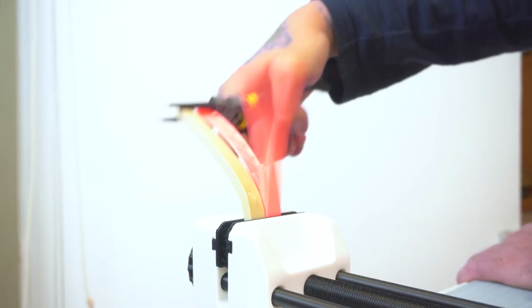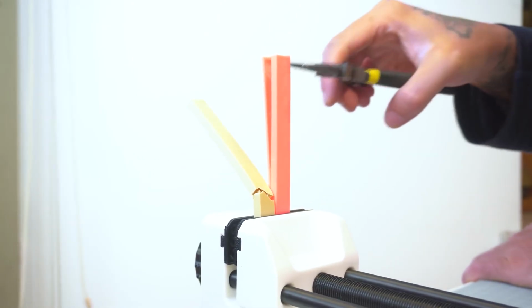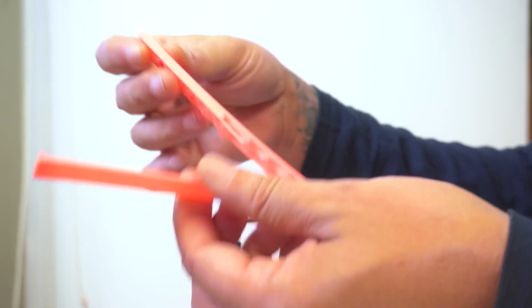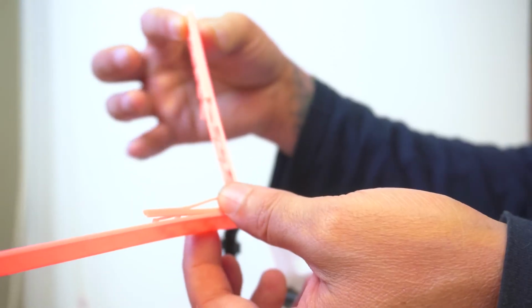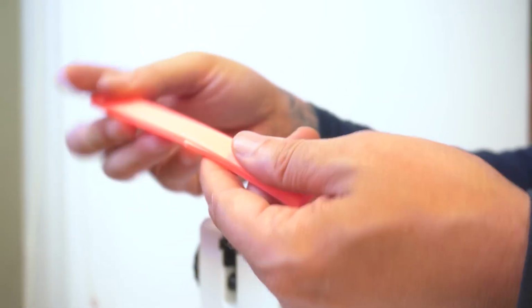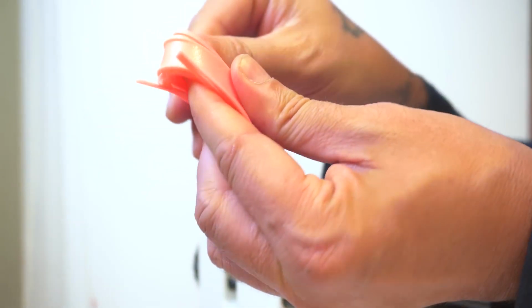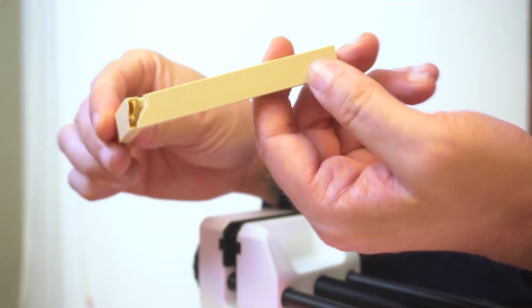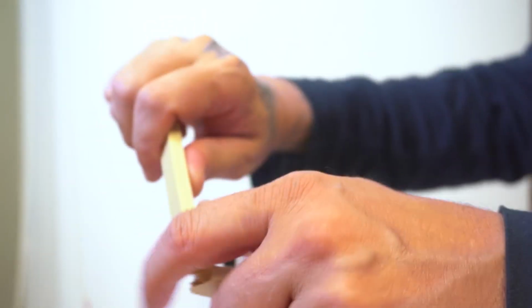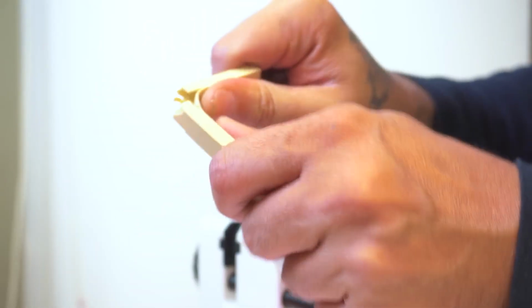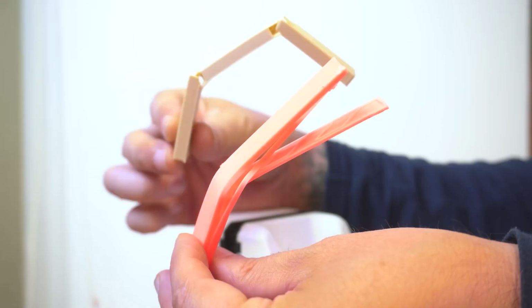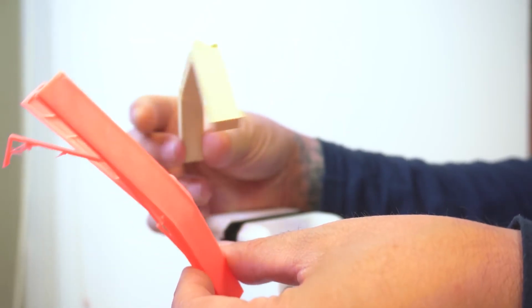we can see the normal PLA, it's completely destroyed. All the layers came apart and there is nothing to use here. Well, and the noise says it all. But the HT-PLA, it's still pretty much intact, and even though it's a little bit broken, it's still soft but also stronger than the normal PLA. In fact, it took me a little bit to break it. And here they are side by side.